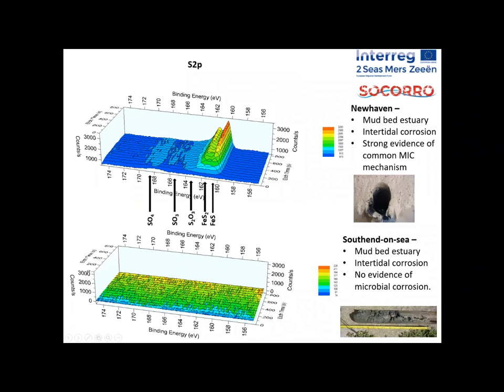And just to make that a little bit clearer, this is a sample from New Haven. It's a contoured plot of the full ablation process. And we can see the outer surface, a very slight sulfate peak there. As we profile deeper and deeper in, we move to sulfide dominated corrosion mineralogy. And we don't see any of that at Southend. So superficially similar environments, intertidal steelwork, but we now have sites we can use to look at what the risk factors are. And you can see we've got a thinner estuarine sediment layer at Southend-on-Sea, but we're working at the moment on establishing exactly why this is different.